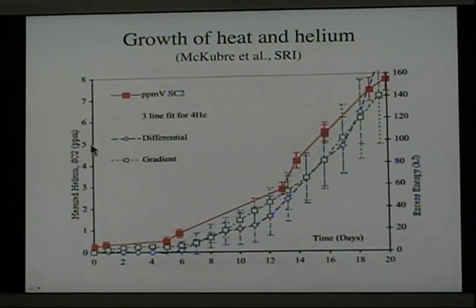Notice that once the amount of helium rose above about 5 parts per million, the gas content had exceeded the content in air, and therefore these samples taken at the higher concentration of helium could not have resulted from an air leak. And the heat production was measured two different ways with good internal agreement. So here again is another clear example of a relationship between helium production and heat production.